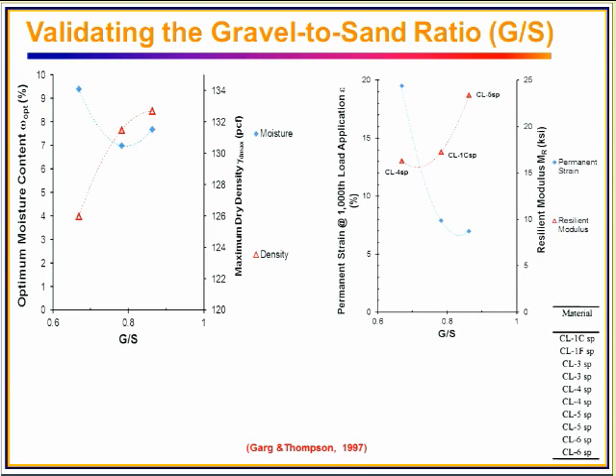Yes, in this figure, it shows just down to, because the maximum GS ratio we can calculate is just between 0.8 to 1. So we were just confirming the trends from 0 to 1.5, in this range. And one quick question: is the y-axis correct? Permanent strain, is that as high as 20%? Looks like there may be a decimal missing somewhere. Probably 2%. There may be an extra 0 there. You can check it later. Okay. Go ahead.